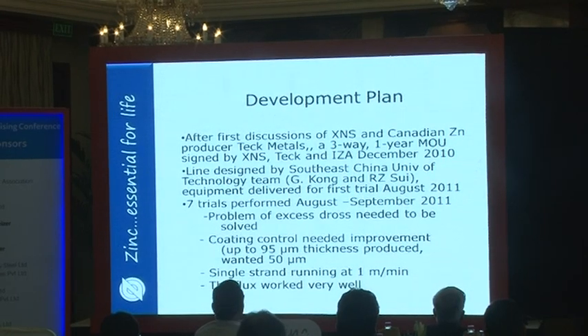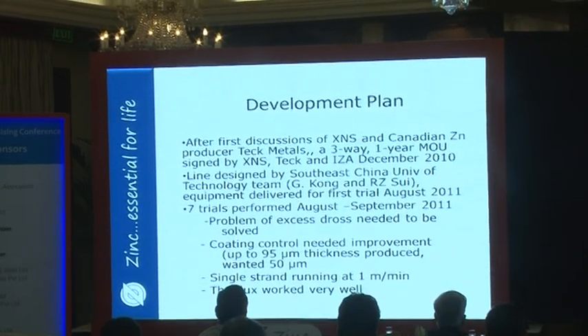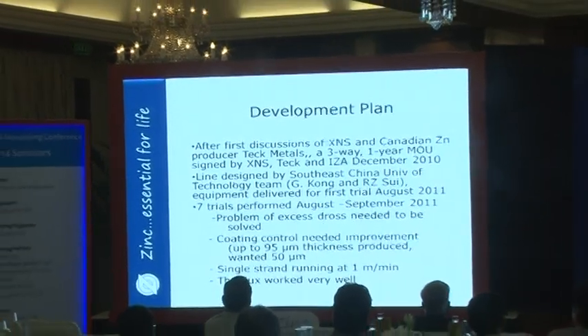We came up with a better galvanizing reaction tube into which we were pumping the zinc, and that allowed for the minimization of the exposure of the liquid zinc to air, and we are now very satisfied with the amount of dross that is being made. It's at about the same level as a normal galvanizing process. So right now we're running about 50 microns of coating. It says here up to 95 microns has been produced. I showed you a micrograph before where it was 10. So we have a big range that is possible here, and we're looking at about 50 microns.